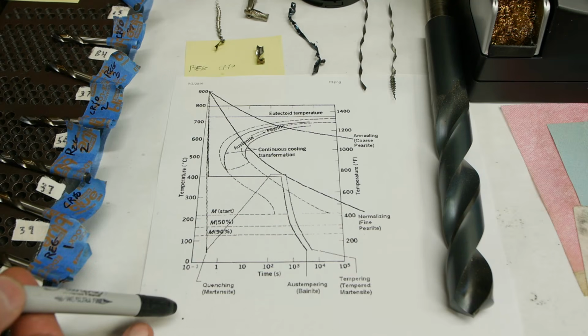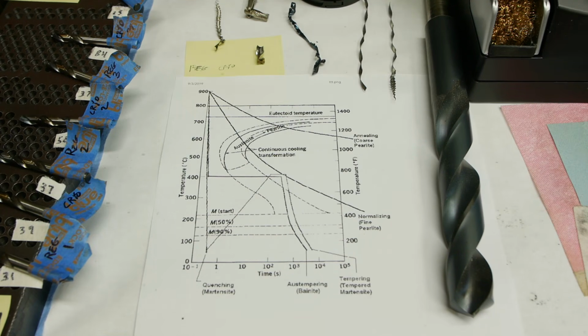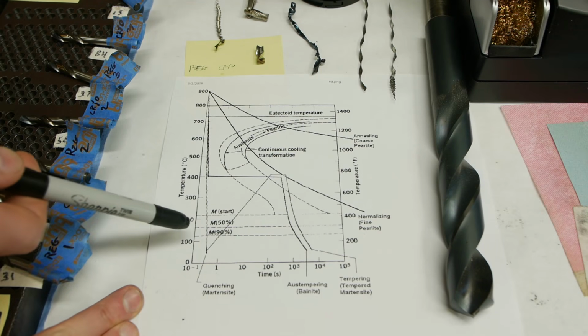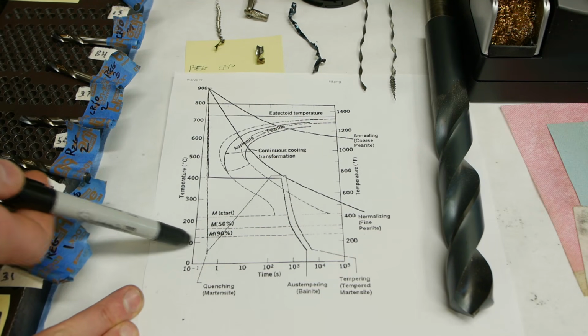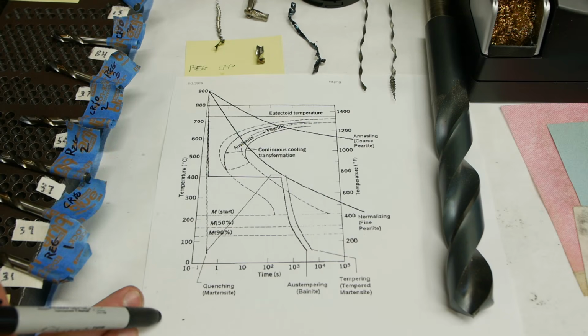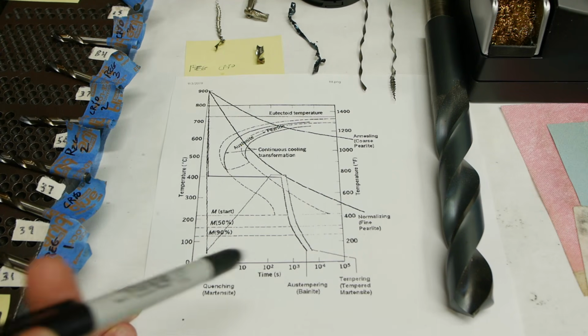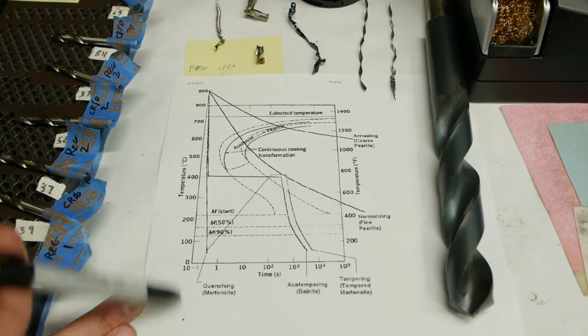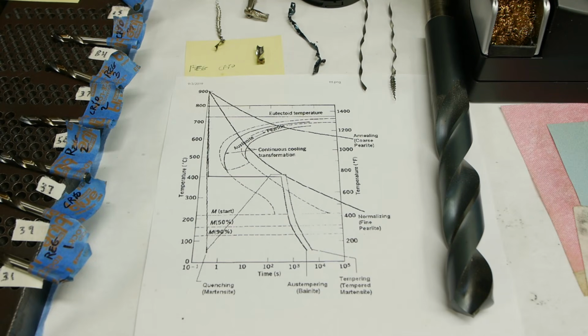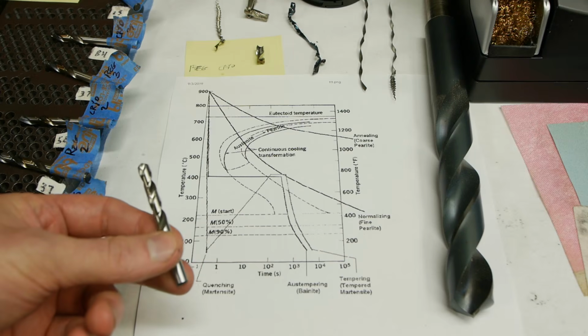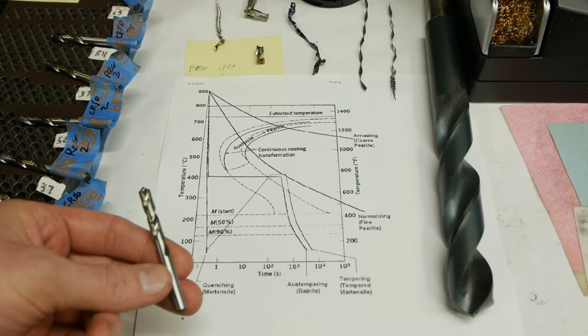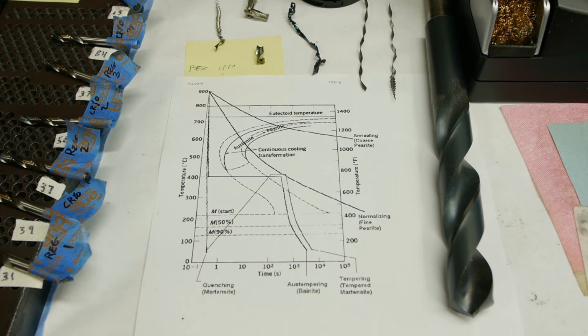And so the first obvious attempt at understanding this cryo treatment is that, well, it's colder, and so if we're only getting up to 90% converted at 110 degrees C or 120 C, if we're down at negative 200 degrees C, we've got to be closer to 100% because it's going up as we go down. And so, at first it seems weird because this drill bit was made months or years ago, and it's been sitting on the shelf, and then it was shipped to me, and then I put it in the liquid nitrogen. It seems like that length of time would sort of erase any ability to affect its heat treatment.